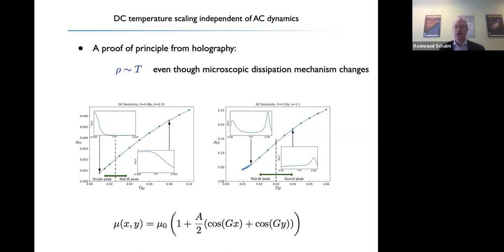Here, however, what I've shown you is an example computed in holography, and I will explain the details throughout the talk, where even though the microscopic dissipation mechanism changes, the resistivity stays essentially linear in temperature. And here's the example. On the left, you see the DC resistivity as a function of T. At very low temperatures, you see a beautiful Drude-like behavior, where I have a linear T resistivity. But the linear DC resistivity persists all the way to a point where, if I look at the optical conductivity, I have some mid-IR peak. This is definitely no longer simple Drude physics.